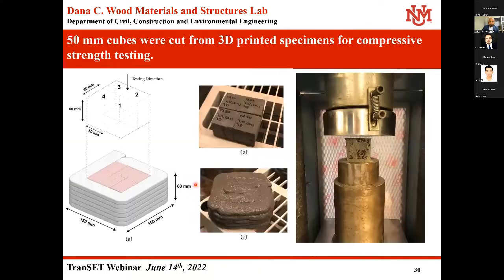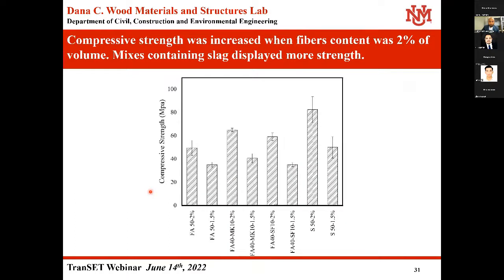In the next phase, we are investigating the mechanical performance of the mixes. First, we measured the compressive strength of 50 millimeter cubes extracted from a printed specimen. The mixes with slag show a better compressive strength as compared to the other mixes. Both had 1.5% and 2% addition of fibers.